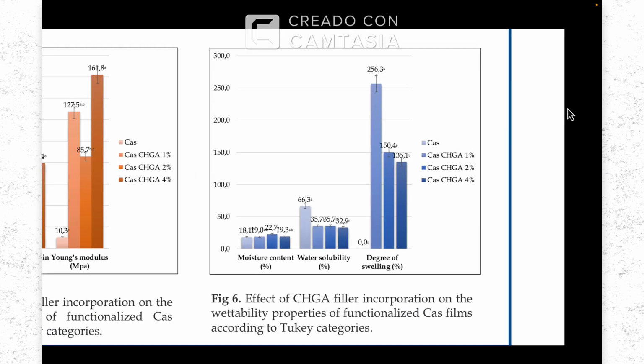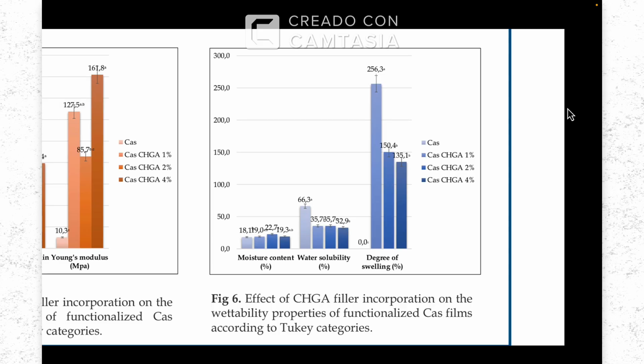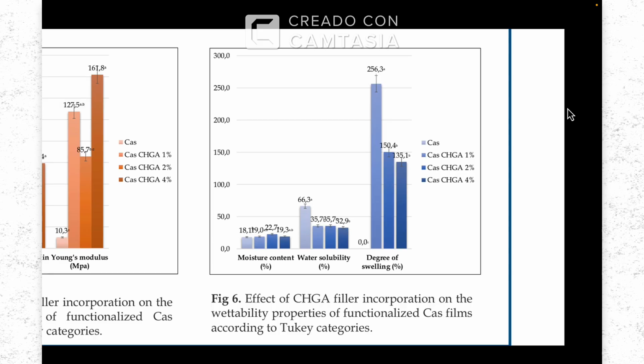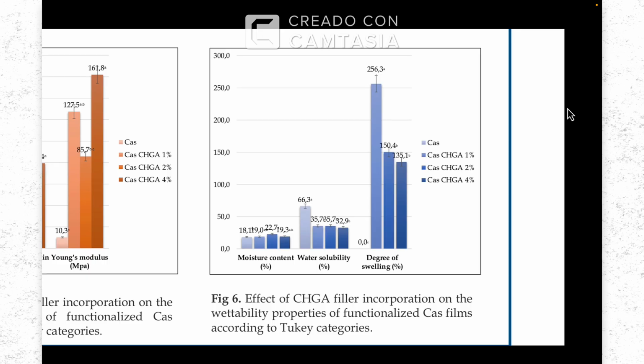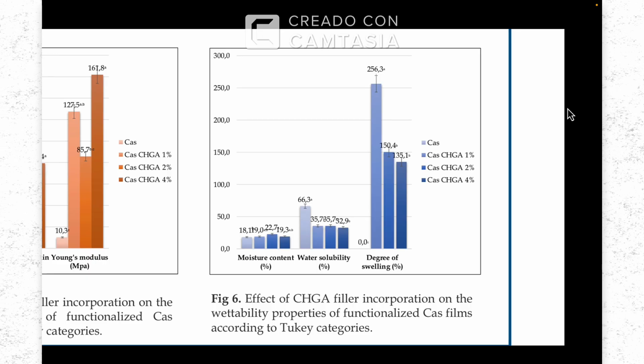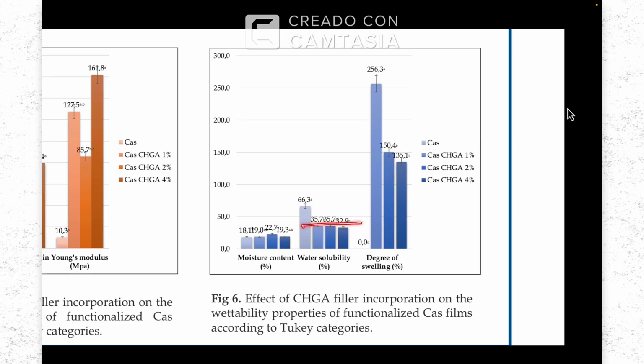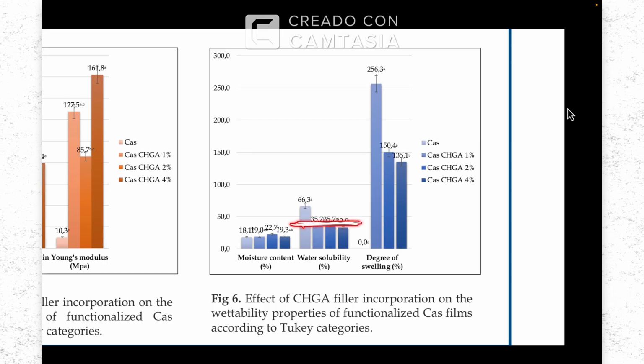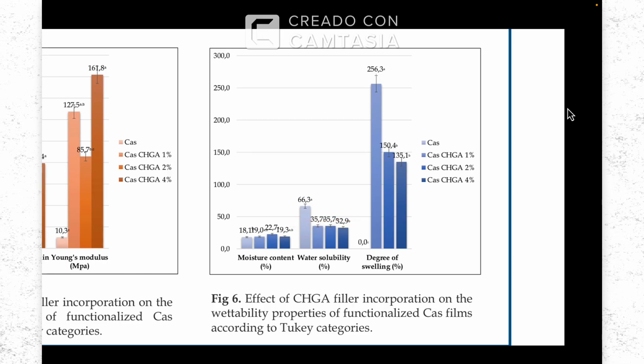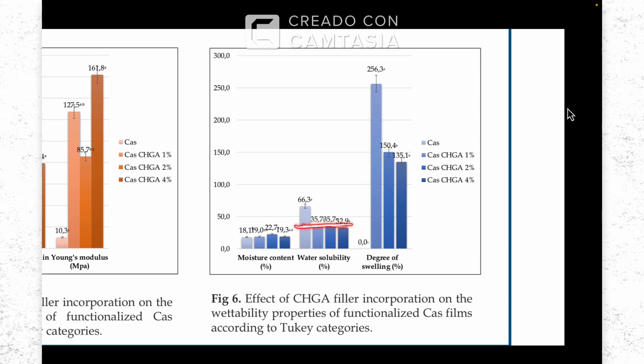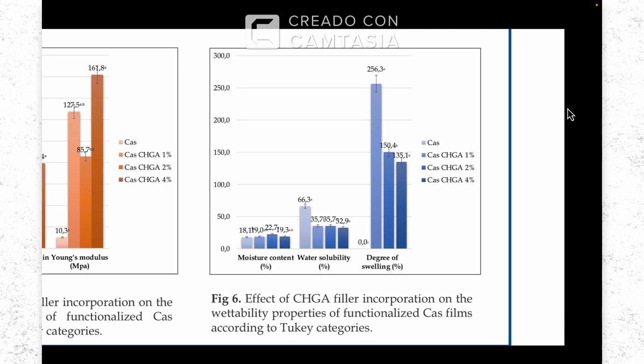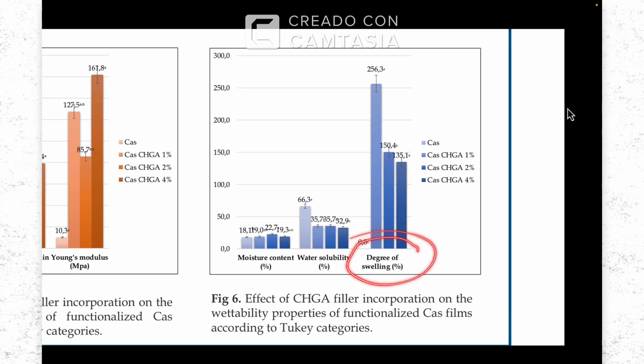The incorporation of the functionalized materials into the films also has a positive impact on water solubility and the degree of swelling. We can observe here that the incorporation of the filler reduces in about 50% the solubility of the films, which is good for packaging application, and we also have a 50% reduction in the degree of swelling.